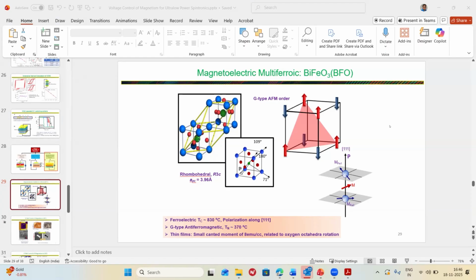I think more than that, the problem is integration in general. Integration of metal on top of oxide is not very great actually. Especially these ferroelectric materials have something called the fatigue issue. When you switch this BFO multiple times back and forth, it creates some sort of fatigue and doesn't switch. The fatigue mostly happens if you use an oxide metal electrode, because oxygen piles up at the interface and creates barriers, Schottky barriers, and that creates problems. So there are other challenging things which are more of an integration challenge.